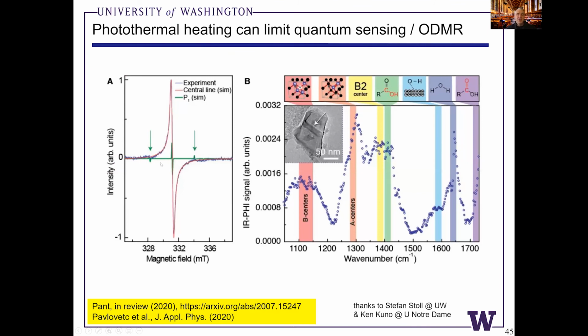And the motivation for this effort is in a lot of diamond materials, no matter how you grow them, they will have defects either in the bulk of the material or on the surface of the material. It's very challenging to get nanodiamonds that are perfectly homogeneous without, for instance, carboxylic acid groups or hydroxyls or other hydrogen passivation or graphitic domains.